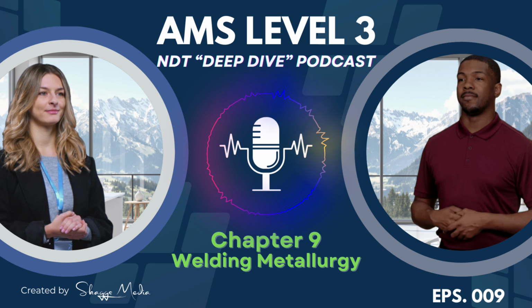In that temperature range, carbon in the steel has a strong affinity for chromium. They combine to form chromium carbides, and these carbides preferentially precipitate right along the grain boundaries. The problem is, this pulls chromium out of the metal immediately adjacent to the grain boundary, leaving that narrow zone depleted of the chromium needed for corrosion protection, so the grain boundaries become susceptible to corrosive attack.